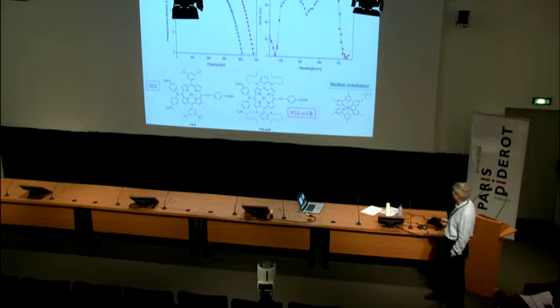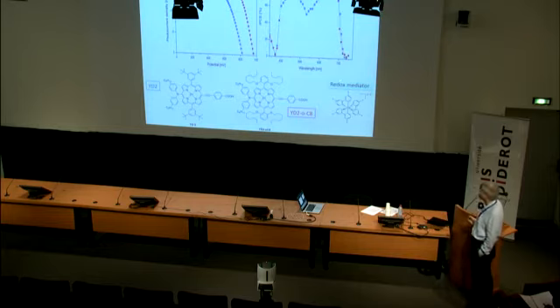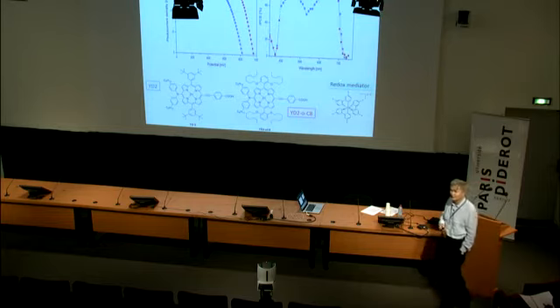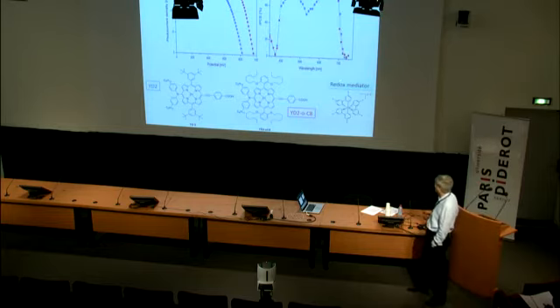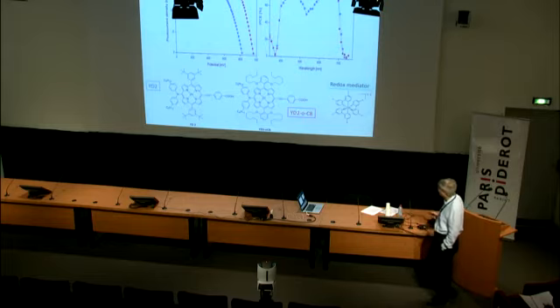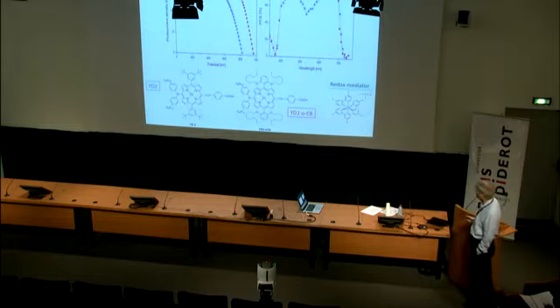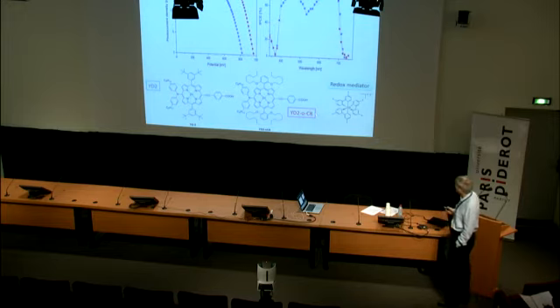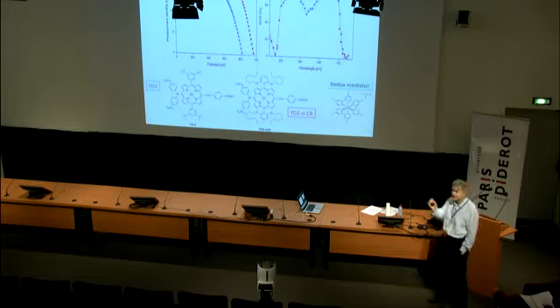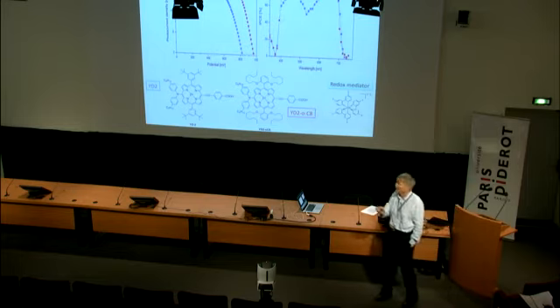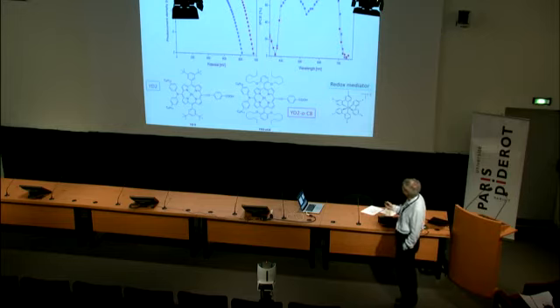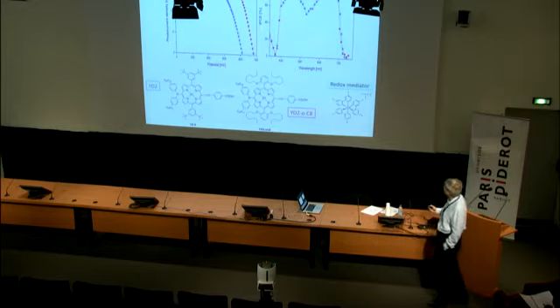response. But then it turned out that if we use a new redox mediator, the cobalt couple, which gives higher voltages than the iodide, this dye, shown here in blue, is by far not as good as the one that has these alkoxy groups. It's coded YD2-o-C8. There's a C8 chain here, two C8 chains. So just note the subtle changes. There are subtle changes in the porphyrin structure which give a dramatic effect on the photovoltaic behavior.